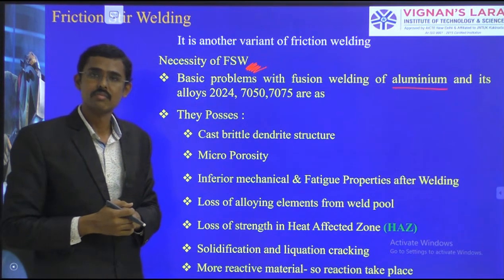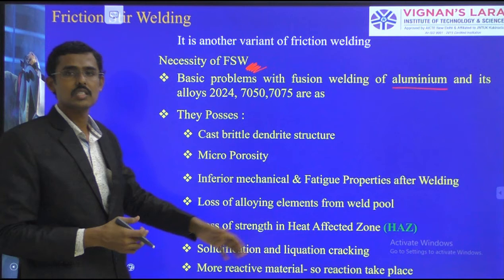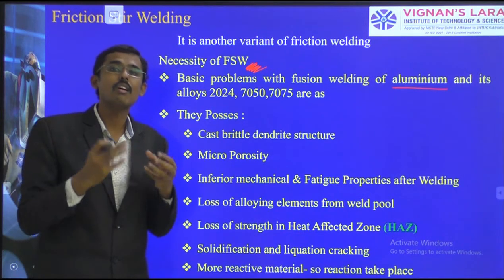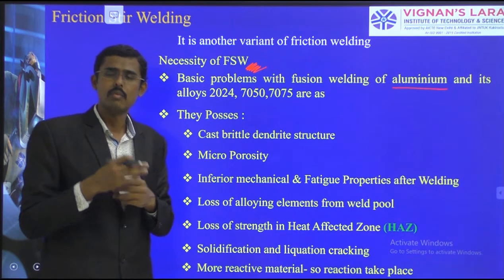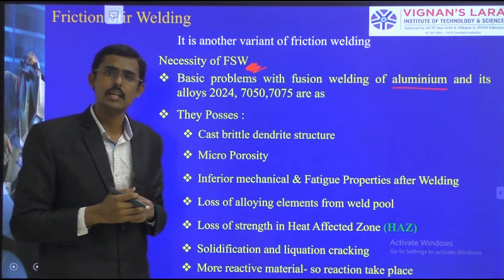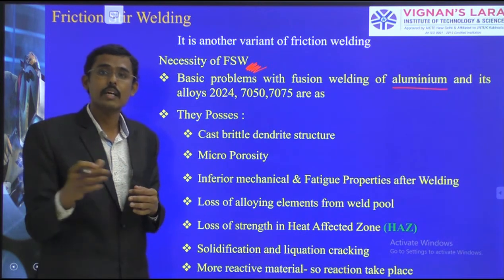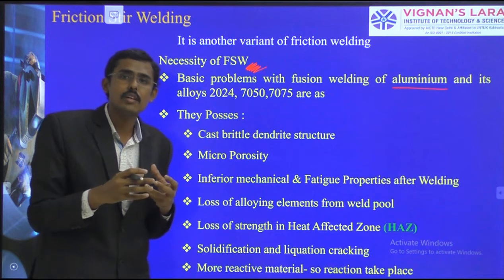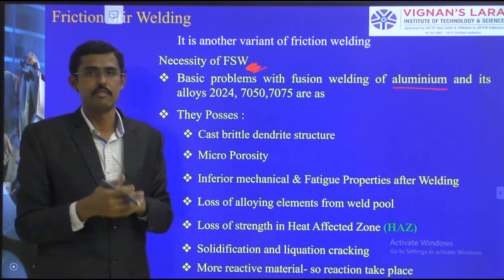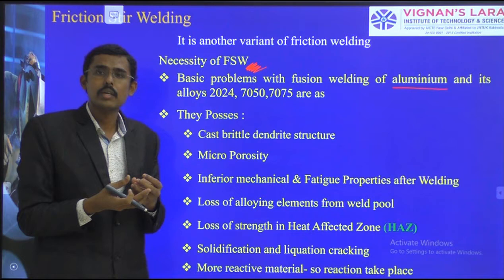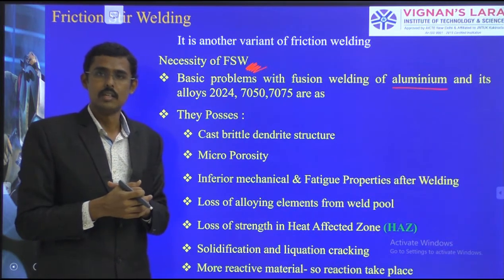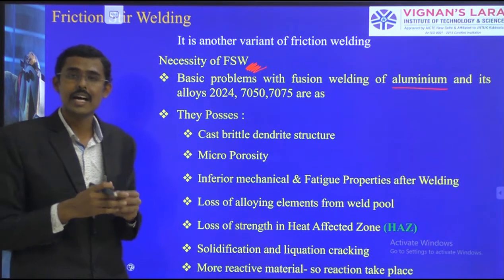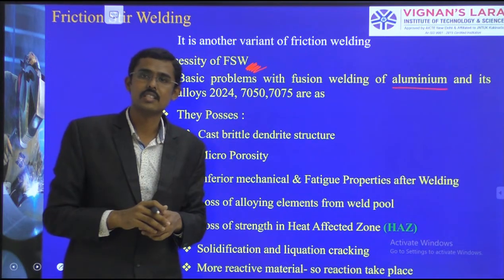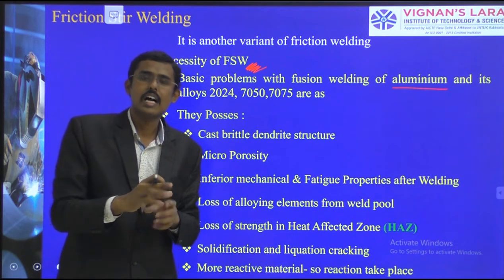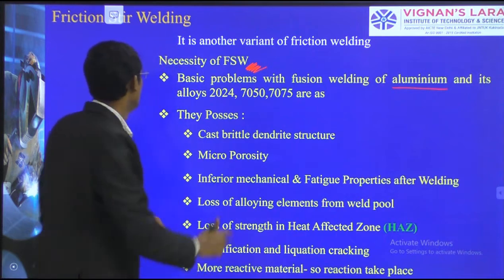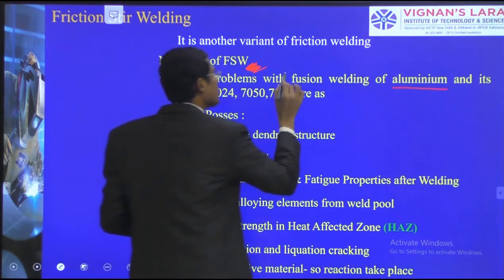That is our agenda. Accordingly, we have formed friction stir welding, which is a solid state joining process which will not reach the melting point of the material, and therefore we are able to weld in the semi-solid or plasticized zone itself. The material is heated and becomes readily deformable. At that time we apply pressure or stirring action and solidify. So that is it. These are the basic problems with fusion welding.